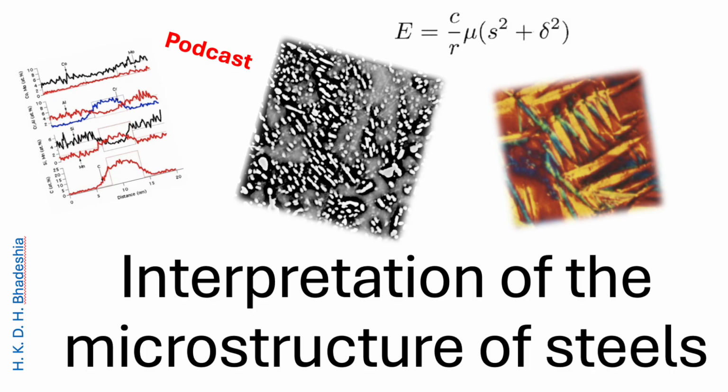It is a violent restructuring. The resulting strain energy is so immense that martensite must form as a thin plate just to minimize that energy penalty. And that massive strain is why martensitic steels are so hard, but also so brittle. And what's the crucial consequence of this disciplined, boundary-confined movement? Martensite plates are absolutely confined to the grain of nucleation, because the organized atomic movement required for the shape change simply can't be sustained across the original gamma grain boundary.